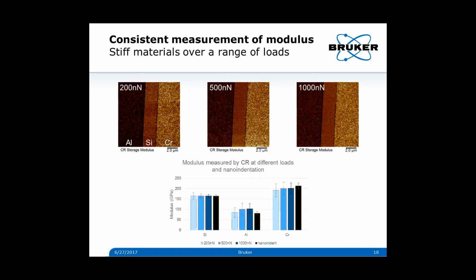Here's another example on the same sample, but looking at different loads. It takes about 30 minutes to collect one of these images. The numbers are very consistent for all modes, so that means that the contact mechanics are working well, and they agree within the error bars. They also agree with the black bar, which is the Hysitron nano indenter. So we're getting really good numbers here.